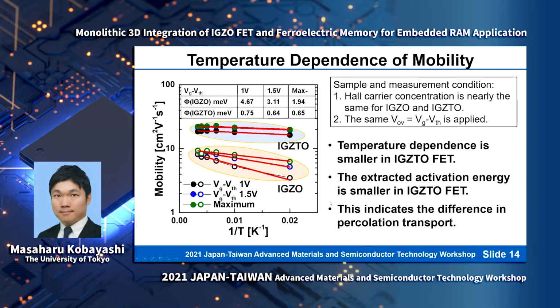To investigate the physical origin of this mobility enhancement, first we study the temperature dependence of the mobility for the IGZTO transistor and the IGZO transistor. So we plot the mobility versus the inverse of temperature, an Arrhenius plot for each transistor's mobility. And as you can see, the temperature dependence is much less in the IGZTO FET compared to IGZO.